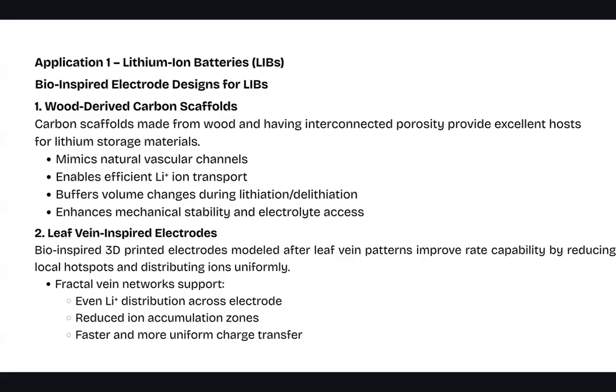So next is the leaf vein inspired electrodes. Bio-inspired 3D electrodes modeled after leaf vein patterns improved rate capability, reduced local hotspots, and distribute ions uniformly. That's how it's achieved. So we have fractal vein network supports. It provides even lithium-ion distribution across the electrodes. It reduces the ion accumulation zones, which are nothing but the dead zones, and gives faster and more uniform charge transfer.